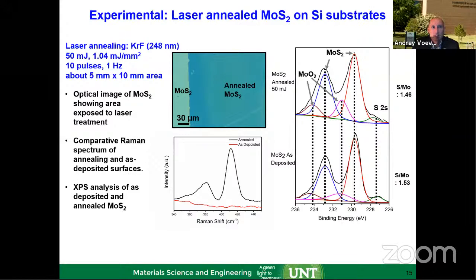And we found that there's actually very little wavelength dependence, but quite a bit of dependence on the density of the power you need to put per unit of the area to anneal, because you want to find that balance, converting it to crystalline material, but not destroying it by ablation or other heating.